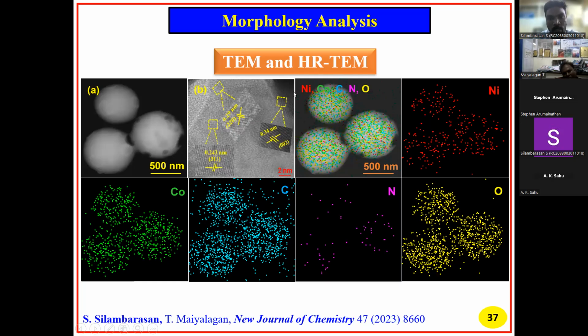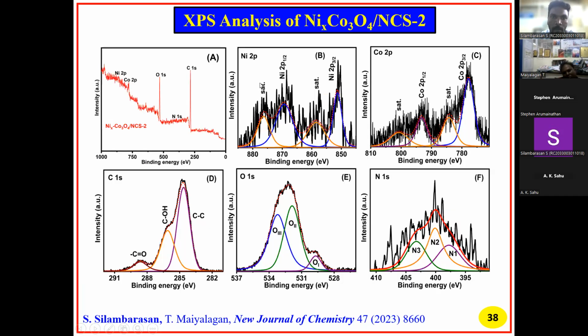Next, the elemental mapping confirms the nickel, cobalt, carbon, nitrogen, and oxygen elements. Next, the XPS spectroscopy. In that XPS spectroscopy, we confirmed all these elements: nickel, cobalt, oxygen, carbon, and nitrogen. Figure A is the survey spectrum we confirmed here. For nickel 2p, the valence states are around 1/2 and 3/2. Then the cobalt 2p, carbon 1s, oxygen 1s, and nitrogen 1s, all these elements confirm the XPS spectroscopy, and the composition is finally confirmed here.